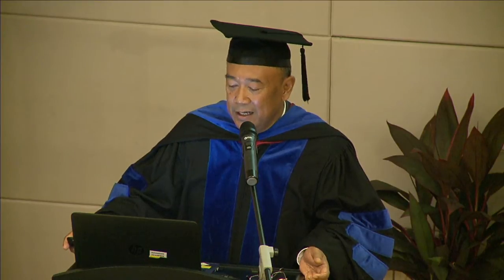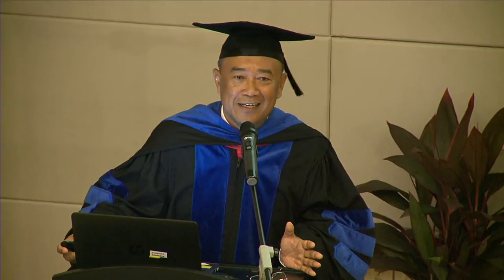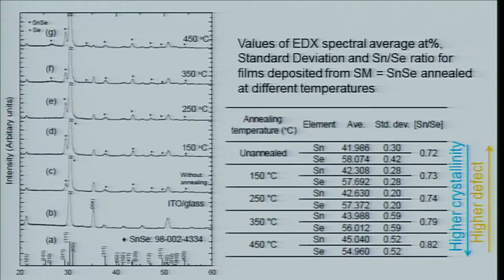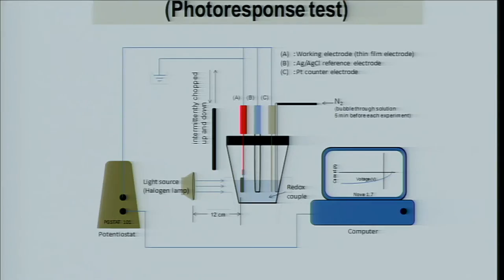Yeah? And thing is, we noticed while we were doing this, that the photo response of the film that have least crystallinity give the best results rather than those with the high crystallinity. So we conclude that most probably the defects in the system helps increasing the photo emission or the photo response of the system. Yeah. And this is we use a photoelectrochemical experiment to test our photo response.